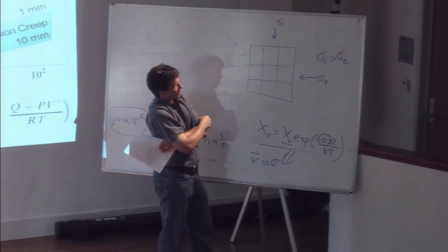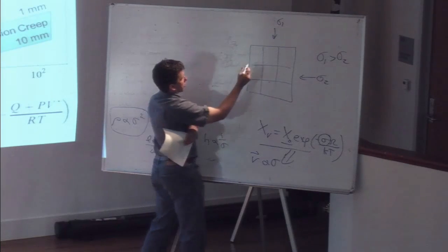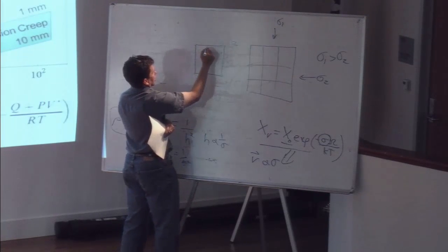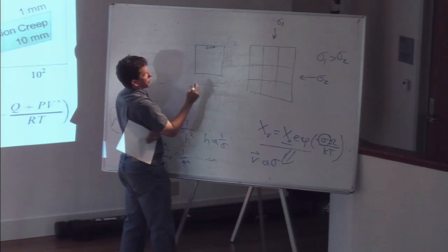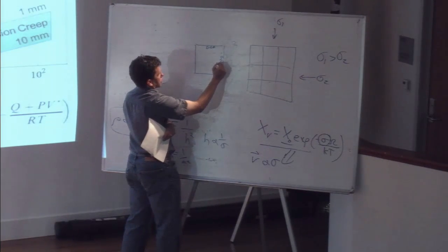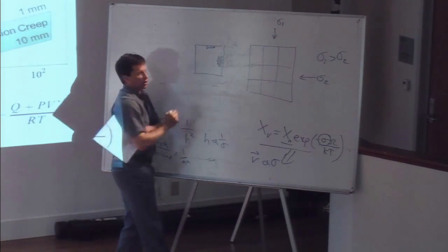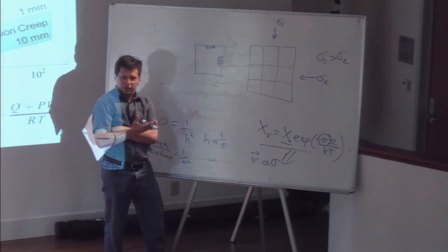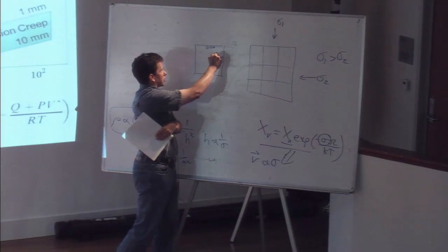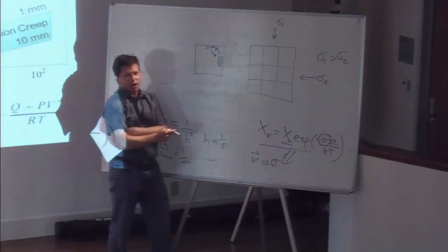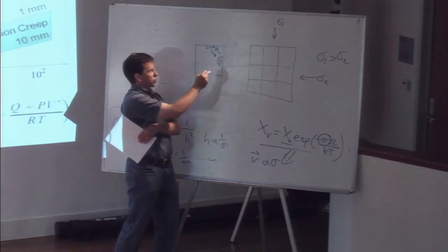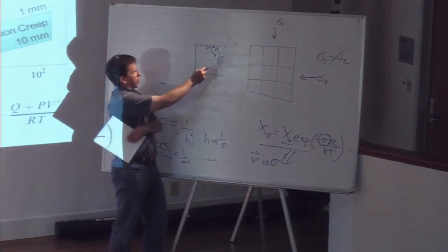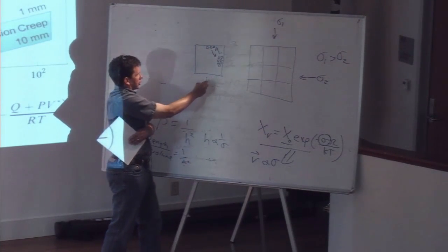So you apply this load, and if you think about what's happening in the stress state, the cartoon you'll start to appreciate is that on this interface with a higher load, you'll have a lower vacancy concentration, these little spots are vacancies, than on the face that has a lower load. So what's going to happen? This drives a flux of vacancies in that direction from high concentration to low concentration and a counterflux of cations and anions in the other direction. As a result, I'm diffusing material away from here and to there,